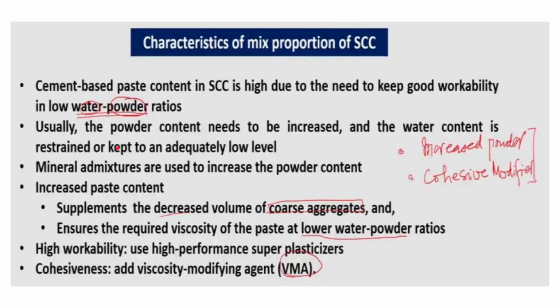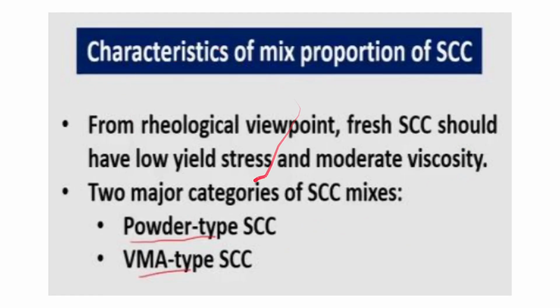Okay, so characteristics of mix proportion of SCC. From the rheological or flow property viewpoint, the fresh SCC should have low yield stress and moderate viscosity. So we get good SCC when the fresh condition of SCC has low yield stress and moderate viscosity. This can be achieved by two major categories of SCC mixes, that is powder type SCC as well as VMA type SCC. So we need moderate viscosity and low yield stress to obtain a good fresh SCC, from the flowing point of view.